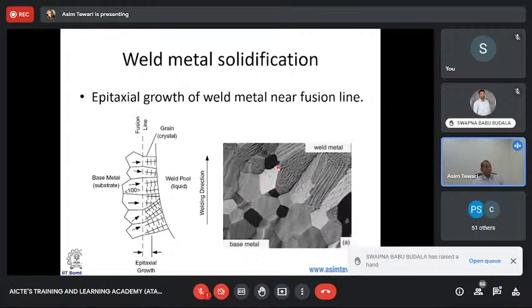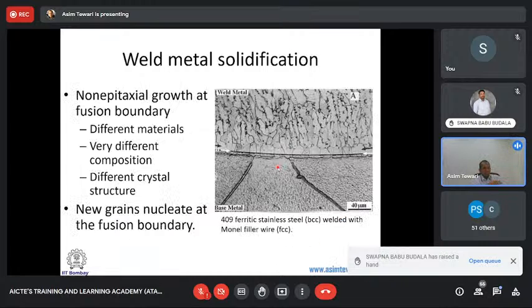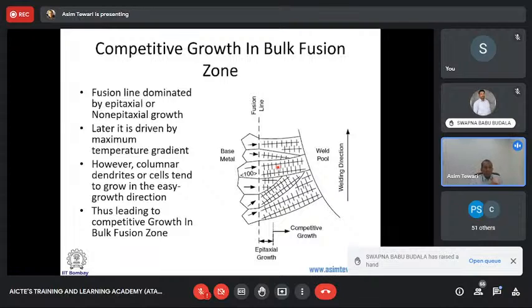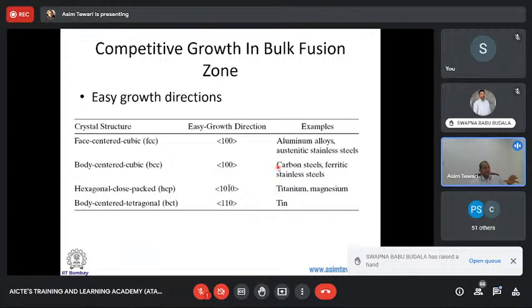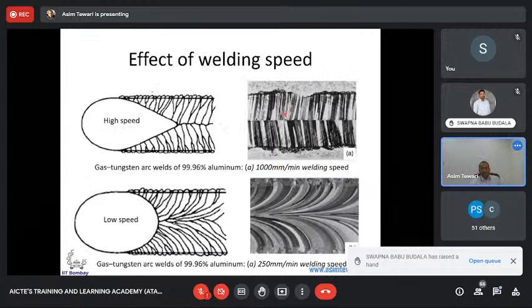And this is dictated by the crystals of the previous layers. But those crystals of the previous layers are very soon, and I'll skip some of these, taken over by the competitive growth because of the orientations. So now the direction of your build is dictated by the geometry, but that also dictates the thermal gradient, and the competitive growth starts happening because of the thermal gradient and the orientation of the individual grains. So you start having some very, very complex microstructures of this kind forming.